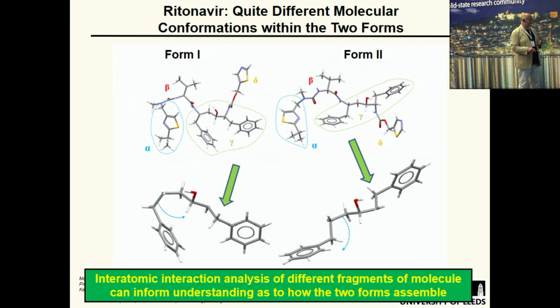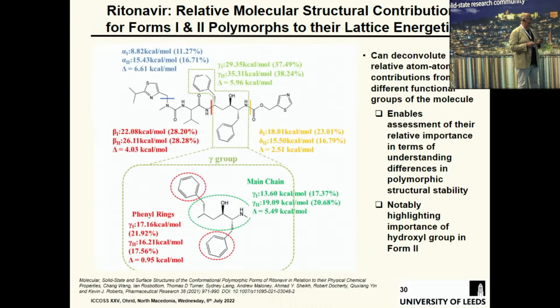So doing that interatomic interaction analysis, you calculate the intermolecular interaction, and then you try and work out which of the interatomic interactions is most important. And here you can see this again in 2-dimensional with the 4 sectors split. If we take this gamma group, we can see how important this central hydroxyl group is, which is much stronger in the form 2 structure than in the form 1 structure. And so it tells us what are the kingmakers, not only in the molecules, but what are the kingmakers or queenmakers in the functional groups between the intermolecular interactions.